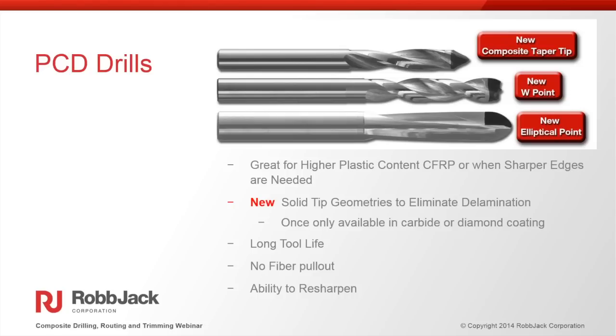The PCD drills are an excellent choice for drilling composites and carbon fiber. The PCD tools tend to outperform the diamond-coated drills in higher plastic content materials. The reason for this is they start and maintain a little bit sharper edge because we're actually grinding those edges instead of growing the diamond on the cutting edge from a sharp edge and then growing it on there. On the PCD, we're actually grinding those sharp edges, so the edges are able to have a little bit sharper cutting edge.